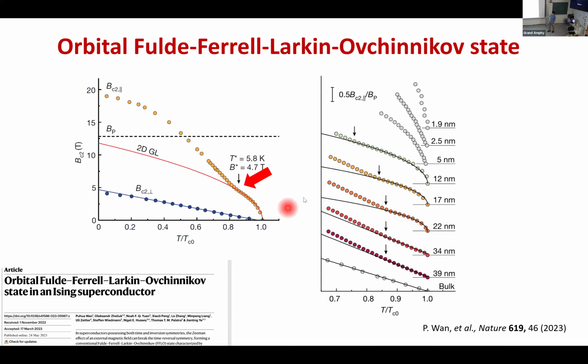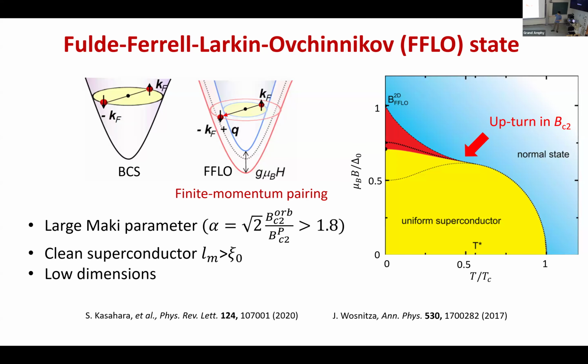Just be a little bit fast. So the other thing people have seen now is, I think, kind of interesting, because at that time many people were focusing on single layer or ultra-thin films because they thought that only in this ultra-thin case you can have interesting physics. However, this paper shows that it's not necessarily so. So you go to thicker films, for example here it's 25, this one 20 nanometers, 22 nanometers. And then they observe some kind of upturn in the upper critical field. Of course, this feature is not so pronounced. However, they also observe something else. This upturn, they claim, is related to the FFLO state.